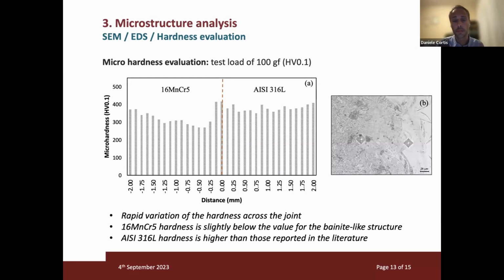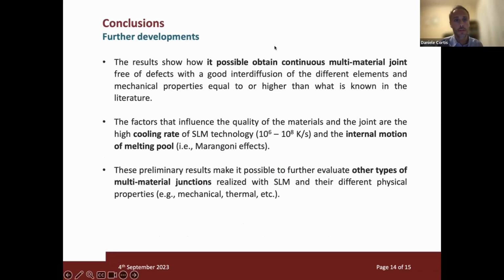Of course, these values are influenced by the speed of cooling, which for SLM is very high, 10^6 or 10^8 Kelvin per second. That influences, of course, the overall mechanical properties. Finally, the conclusion of this work: it's possible to obtain very good joining between two materials, free of defects. And as I said before, the cooling rate is one of the main factors that can influence the structure of the junction and can generate some internal motion of the melting pool that is very hard to study or simulate for a single material.